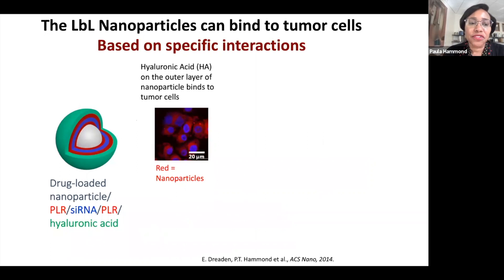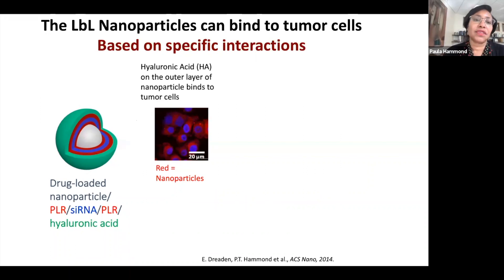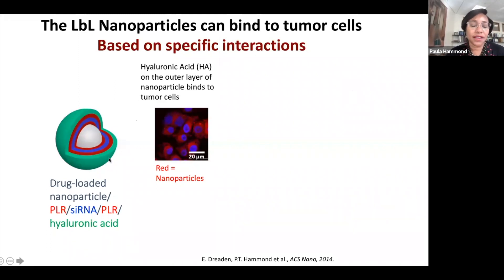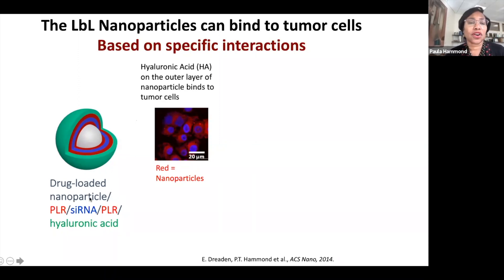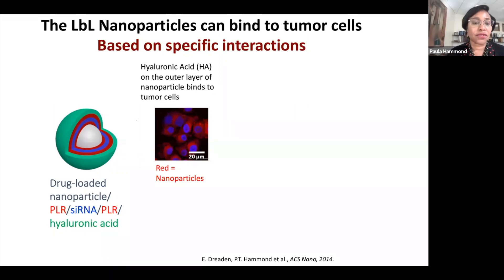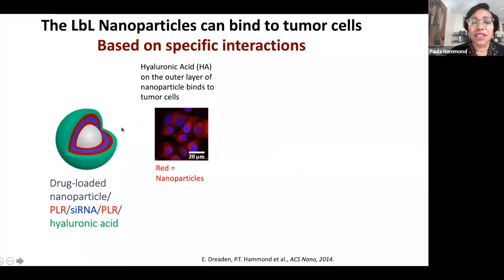It's also possible to select polyelectrolytes that have affinity for the cells we're trying to target. One straightforward way is to use a polysaccharide like hyaluronic acid as the outer layer. HA is very well hydrated and strongly negatively charged, but it is also a native ligand for CD44, a receptor highly overexpressed in a number of cancer cells. We can use HA-coated nanoparticles to target solid epithelial cancers including triple negative breast cancer, non-small cell lung cancer, glioblastoma, and ovarian cancer, using this as a tag to get into the cells.